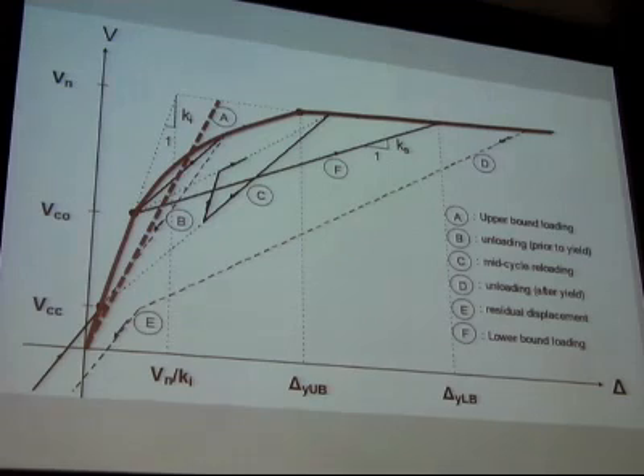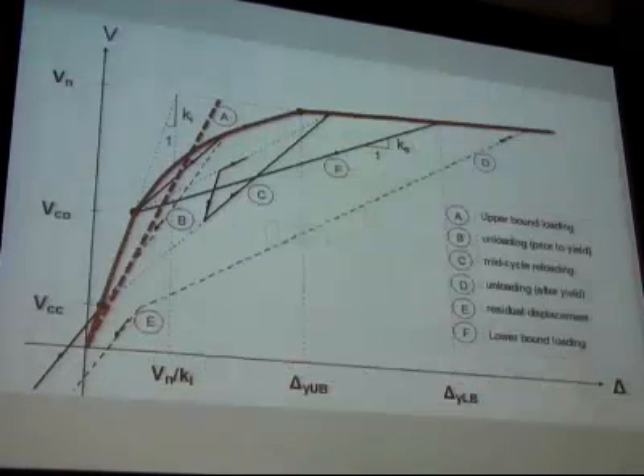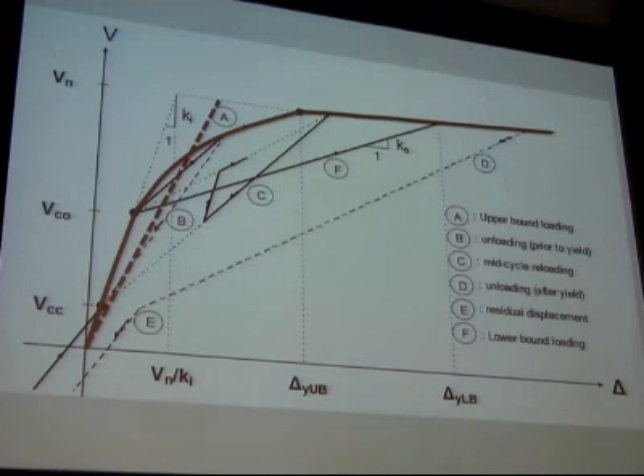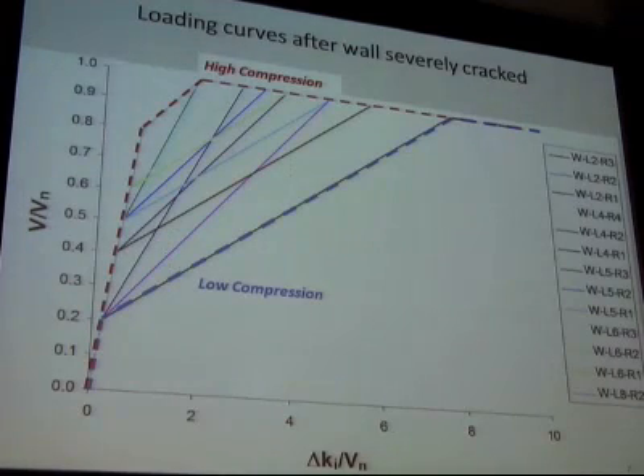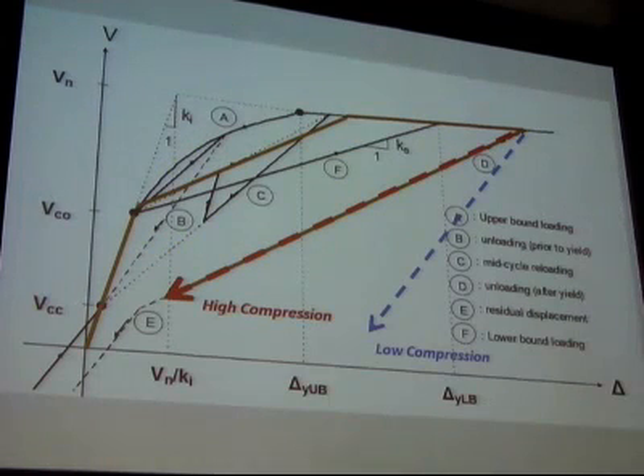Okay. So we've been investigating this for a few years now, and this is a load deformation response of a typical shear wall. Okay, and if you look just at the loading envelope, actually the idea of using that expression as a function of the axial load makes a lot of sense, because here's what the load deformation responses look like for a number of severely cracked walls. And a wall that has high compression has a loading envelope that's actually quite steep and goes up quite high. And if you have low axial compression, you crack much earlier and you get a much softer response. So that's where that equation comes from and actually makes a lot of sense.